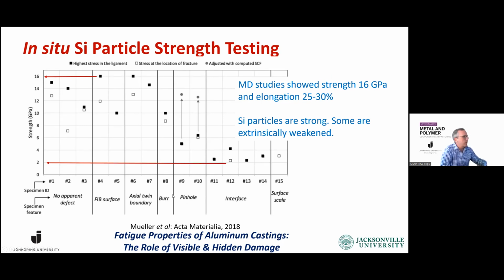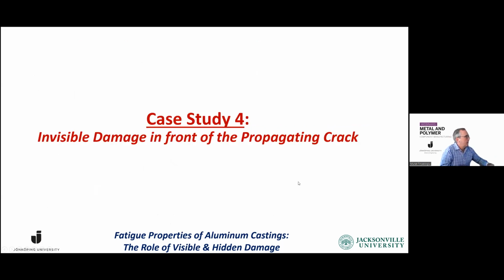Yes, in certain instances, they were weakened extrinsically, but the strength went down to about 2 gigapascal. Maybe there was an interface or there was a pinhole in them, but it never went to 160 megapascal. So again, we reached the same conclusion. Silicon particles are strong, but some of them are extrinsically weakened because there's a bifilm going through right in the middle. Okay, case study. Tony.